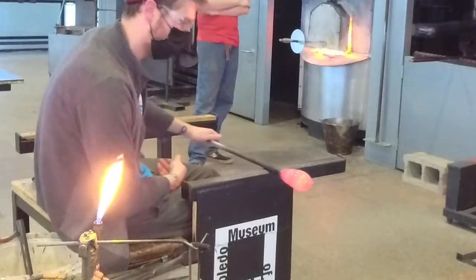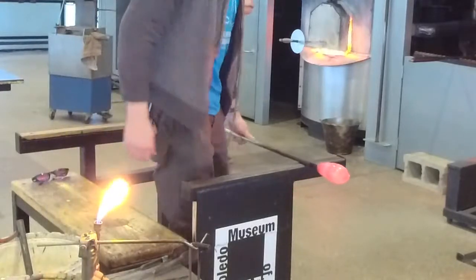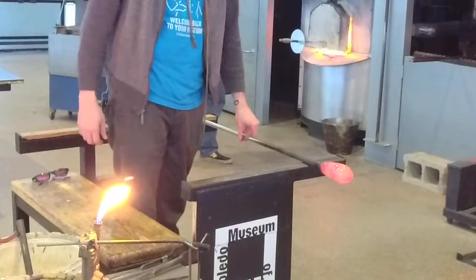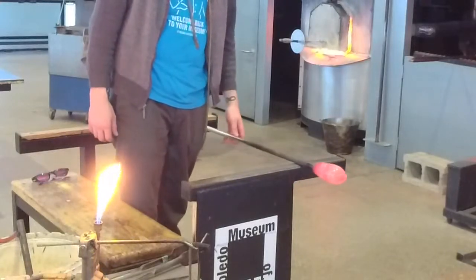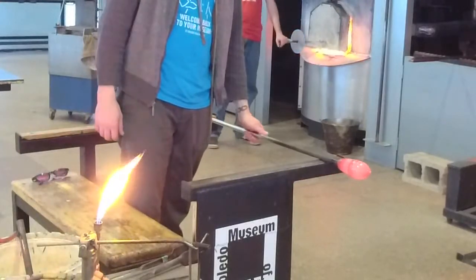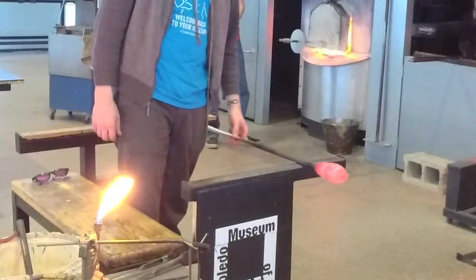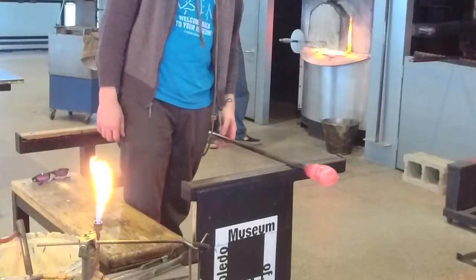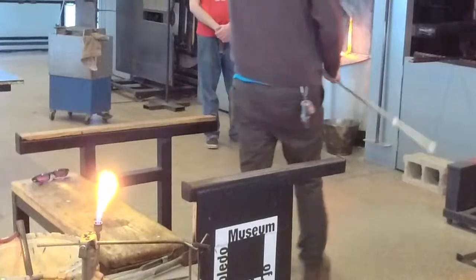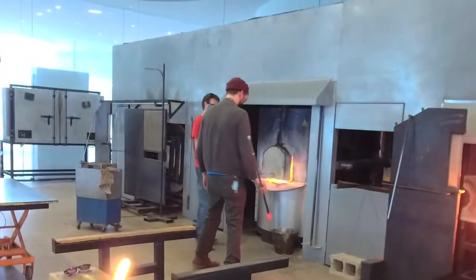So he's going to let it cool down before he goes in for another gather. If your glass is too hot when it goes into the furnace, it could heat up even more, and you can kind of lose your shape as you go. So you want it to be just cool enough that it's going to have a nice firm structure underneath.